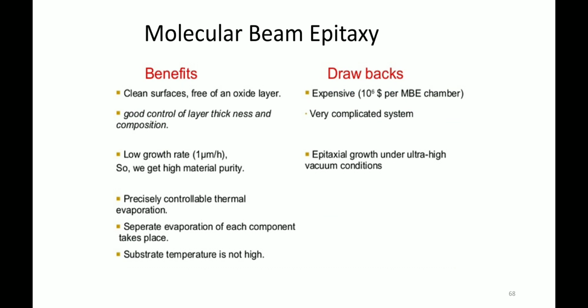Okay, so these are the advantages and disadvantages of molecular beam epitaxy. As you can see, there are several benefits of molecular beam epitaxy. That is a clean surface which is free of oxide layer. Okay, so whatever you are getting, the quality of the final product is not oxidized. You get very high quality thin films. Second is the good control of layer thickness and composition. Low growth rate, that is 1 micrometer per hour in most epitaxial growth. If you want a single crystalline epitaxial thin film, then the growth rate should be as low as possible. Okay, so you get a high material purity and precisely controllable thermal evaporation, with separate evaporation of each component taking place.